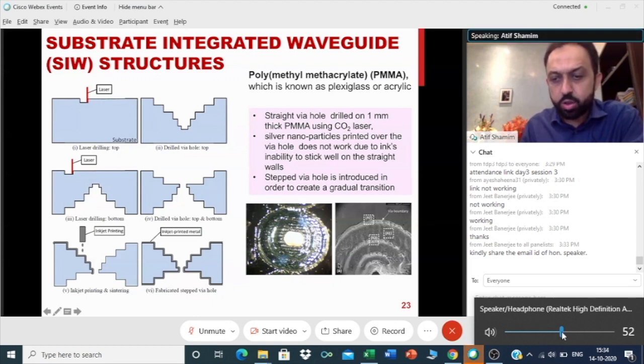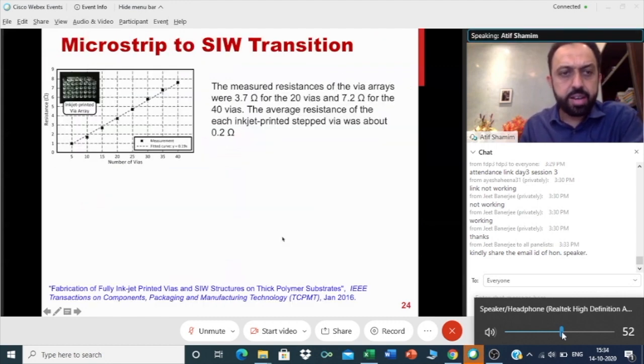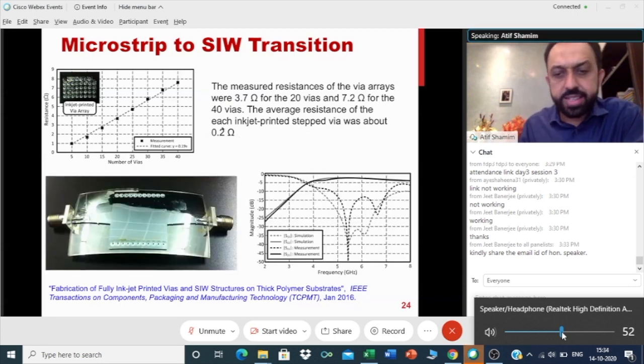We created vias. You can see these SEM pictures of the vias we created, very nice. And we made complete arrays of these printed vias, and then we characterized them. We saw that overall the resistance created by each via was very small. So they were very much usable as you would use vias in a printed circuit board. Once we did that, we did a lot of work on SIW kind of designs.